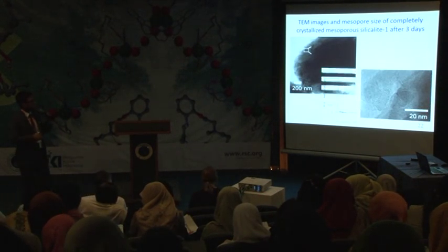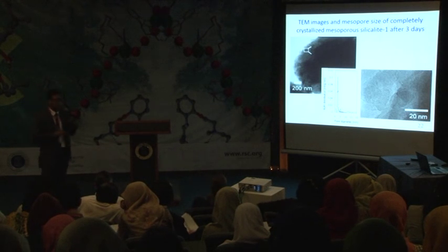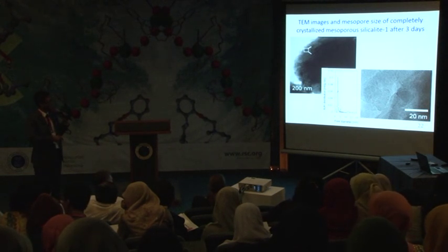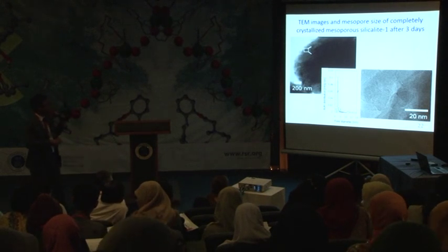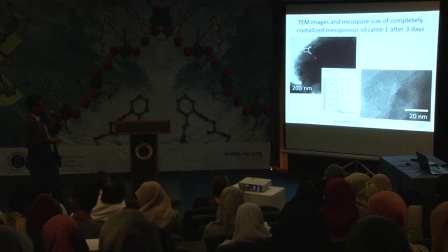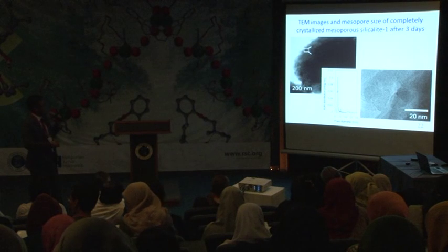We also characterized this crystal using the transmission electron microscope, and we could see some lattice fringes, confirming that there is a d-spacing of zeolite here. And the pore size distribution seems to agree with a nicer, better picture of this, showing probably a 2 nanometer mesopore size.